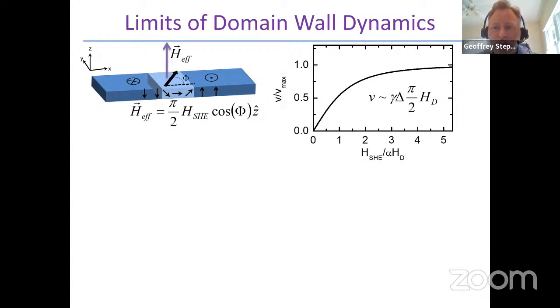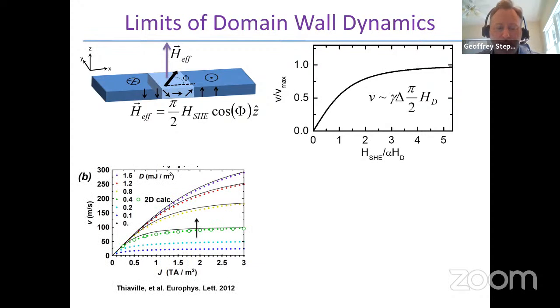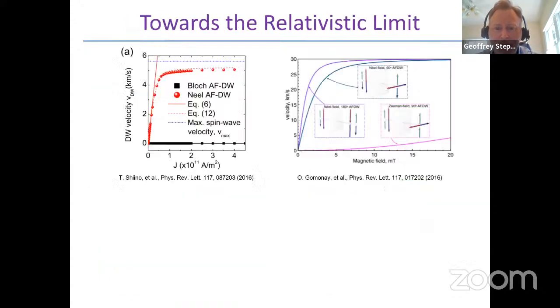If you apply a magnetic field along the stripe, you can increase the stiffness and you can increase that domain wall velocity. And that's been shown experimentally. So fundamentally, for conventional domain wall dynamics, the maximum speed is proportional to the stiffness of a wall. But eventually that has to give way. A domain wall can't move infinitely fast. And you could apply in principle an infinitely large magnetic field to give an infinite stiffness to a wall. So what then limits the absolute maximum velocity that a wall or a spin texture can take?